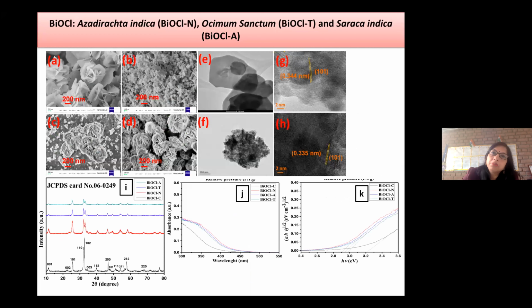First of all, I'll take the bismuth oxychlorides. The bismuth oxychlorides were prepared using different leaf extracts like tulsi, ashoka, neem, and also by the simple hydrolysis method. The conditions were the same for all the materials prepared by the four methods. The method was hydrolysis, but with different leaf extracts. This is the SEM image of BiOCl prepared by only the hydrolysis method without adding any leaf extract. B, C and D are the SEM images of BiOCl prepared with neem, tulsi and ashoka leaf extracts. And E and F are TEM images.